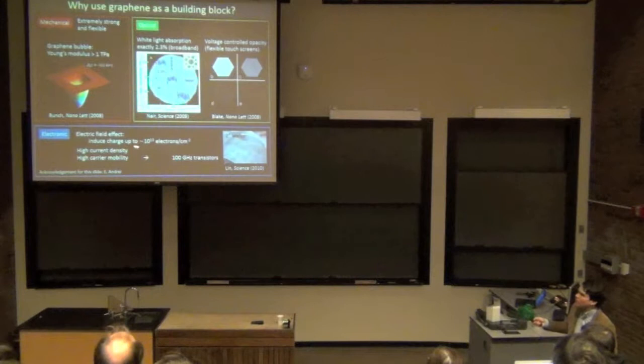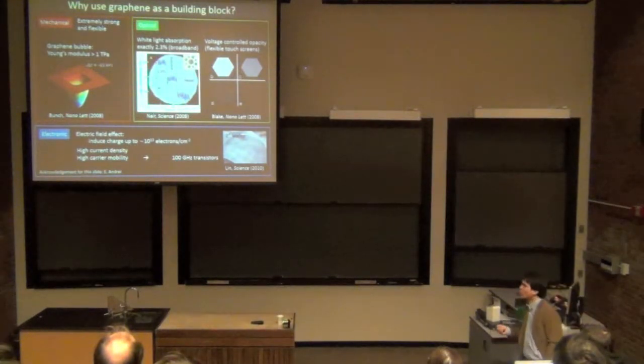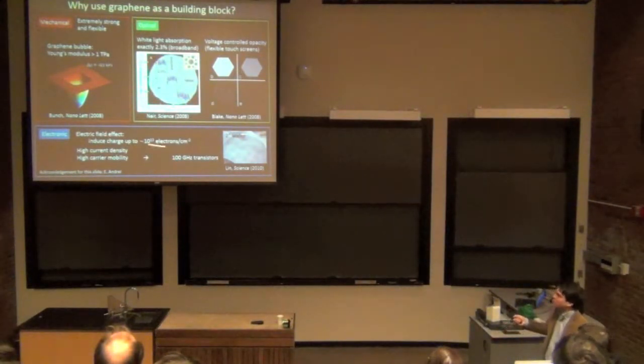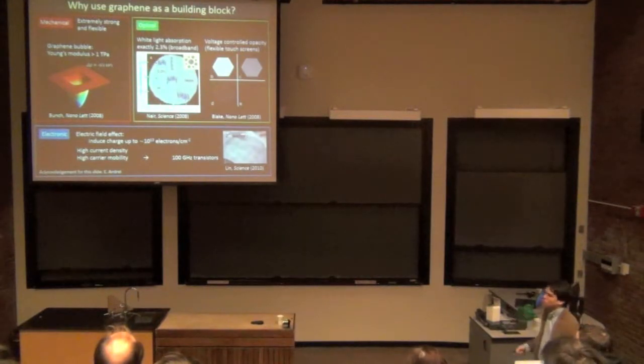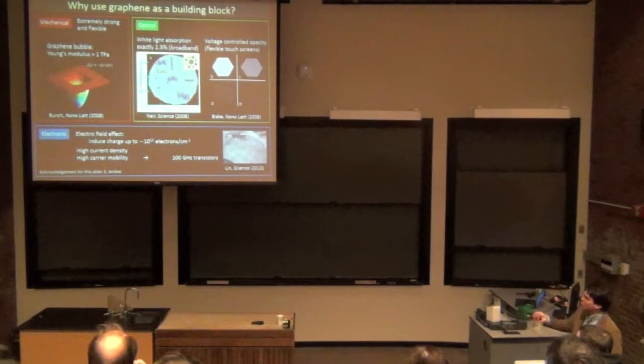And then from the electronic properties point of view, because it's very thin, you can induce immense amounts of charge in the layer that change over three or four orders of magnitude, up to 10 to the 13 electrons per square centimeter. And this goes along with an extremely high current density and a high carrier mobility, which allows you to make high frequency transistors. So graphene really is quite a miraculous material.